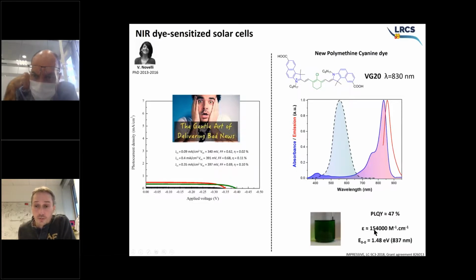quantum yield of 47%, but it has a very, very high molar extinction coefficient, 150,000 liters per mole per centimeter. Vertical excitation is very close to the band gap value, 837 nanometers. So that's the reason why the molar extinction coefficient is that strong. You do see a green coloration in solution that you will not see if the cuvette is a few tens of micrometers thick.